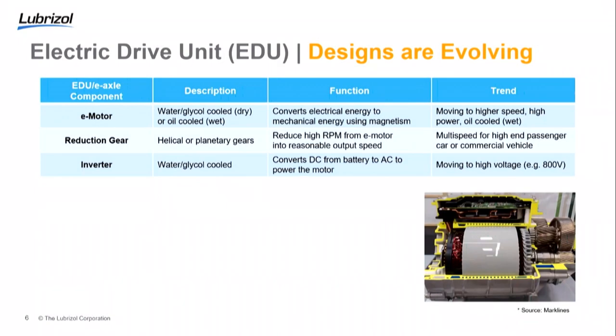The inverter can be water or glycol-cooled, and that converts the DC from the battery to the AC to power the motor. The trend here is moving to high voltages, so for example up to 800 volts or maybe even higher, and that allows the systems to run cooler and be more efficient. What often happens there is the copper wires become thinner, and then the fluid needs to take care of the copper corrosion.